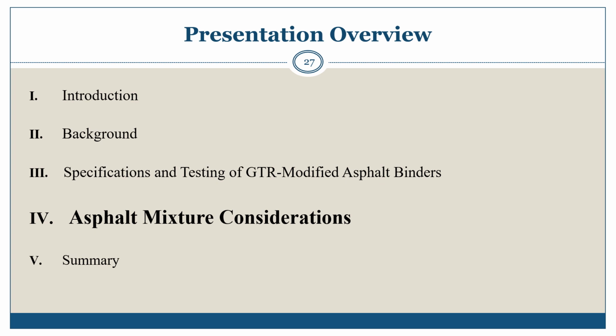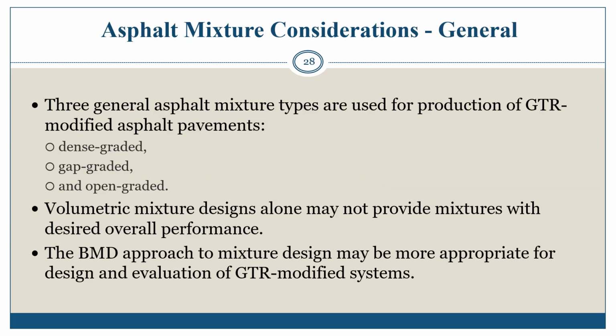Asphalt mixture considerations. GTR modified asphalt binders have been successfully used in the three general mixture types: dense graded, gap graded, and open graded mixtures. Mixture design volumetrics are important in design of mixtures containing GTR modified asphalt binder or dry added rubber. However, volumetric mixture design procedures may not provide mixture performance desired. It is important to consider the rubber component of the binder and how much it affects volumetrics. The BMD approach may be more suited for a design of GTR modified systems.